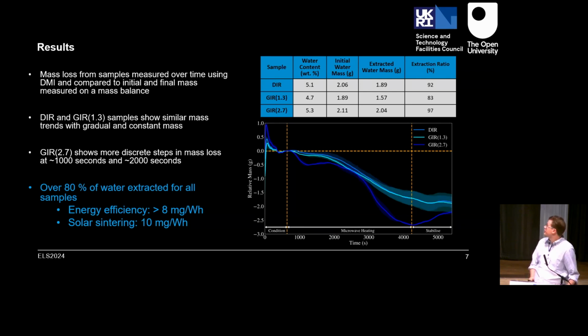And then if we look on the bottom right, we can see the graph of mass loss over time using the mass instrument. And luckily, the graph actually shows it. I was very worried it was going to be a black box. For the first 600 seconds, there was no microwave heating on. This was just to allow the mass instrument to get a consistent result and also to check that the mass wasn't being lost too quickly in the vacuum of the system. And then there was about an hour of heating, where for the diffuse ice and the smaller grained granular ice, the trends are fairly consistent, which to me suggests that at the smaller grain sizes, it's almost acting like a well-diffused, very well mixed ice. And then for the larger grain sizes, we see two significant drops of extraction, which again suggests that it's doing something differently to what the other types of ice were doing.